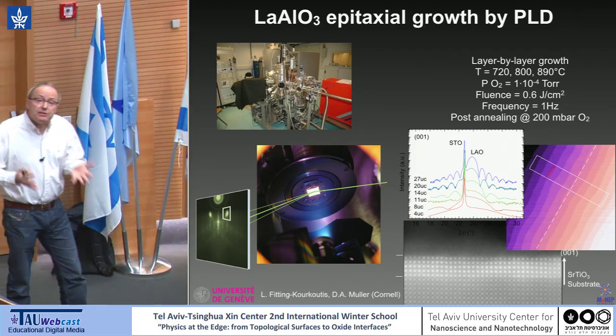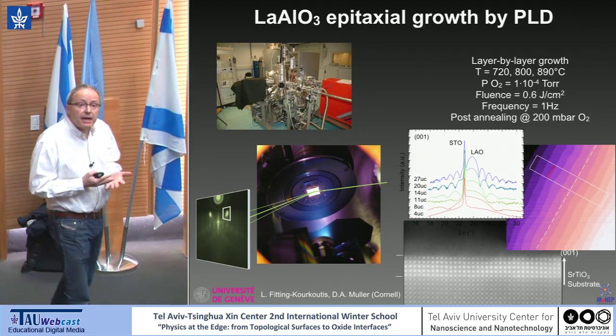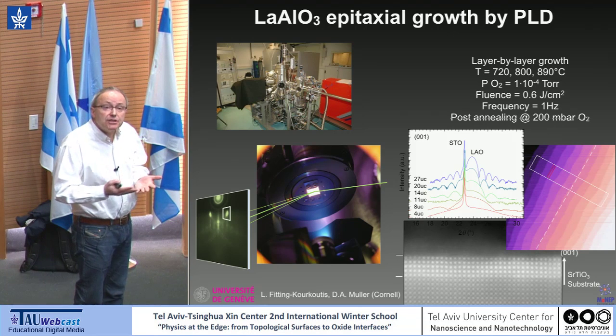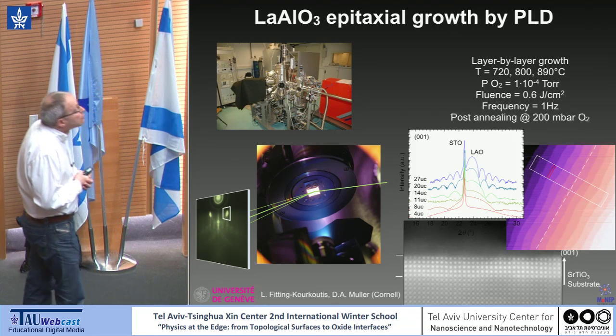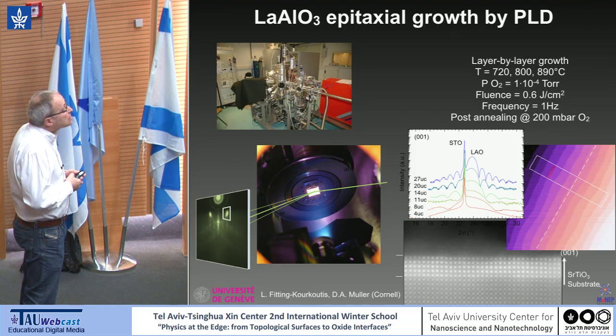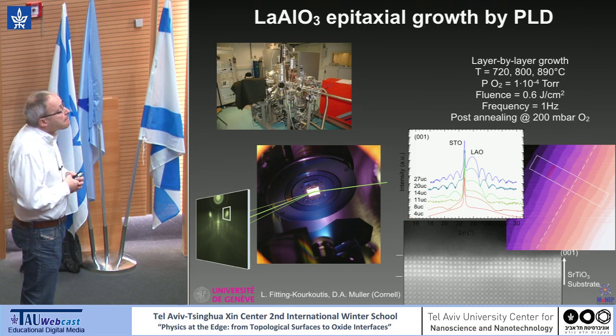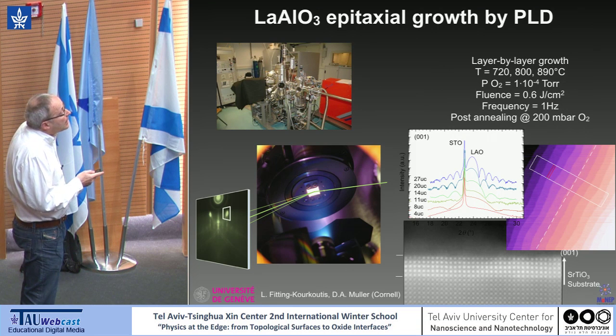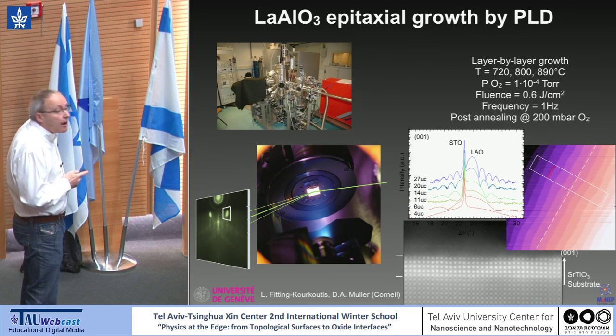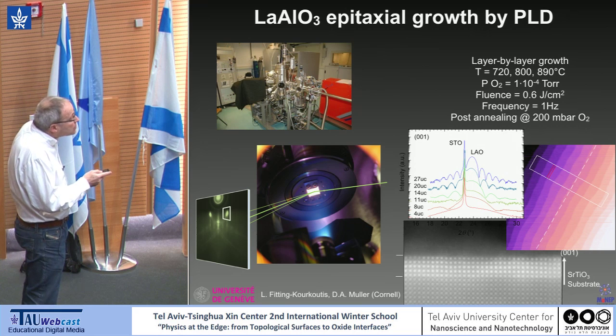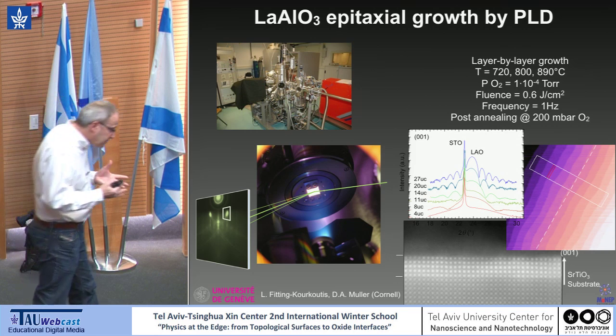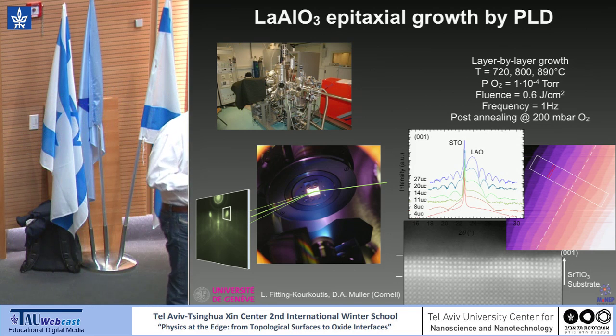What we do, we start with a single crystal of strontium titanate, 001, which is TiO2 terminated, and we grow using pulse laser deposition a very thin layer of lanthanum aluminate. Typically, we use 800 degrees C in some partial pressure of oxygen. Now, what is important is that when you heat strontium titanate, very often you generate oxygen vacancies.